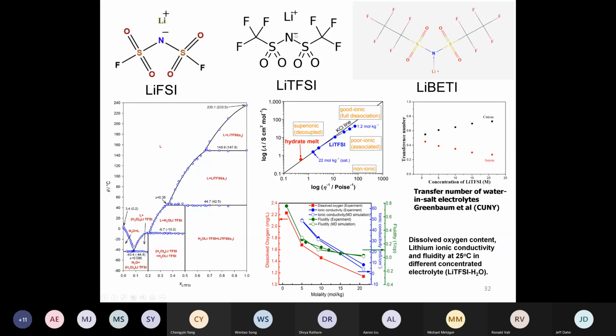The unique thing about these salts is that the anion is bulky and soft, and more importantly, the polarization of the whole anion is well distributed. That means when the lithium salt forms a crystal, the lithium has multiple sites to associate, which means this salt is very easy to dissociate in the solvent and very hard to form a good crystal.